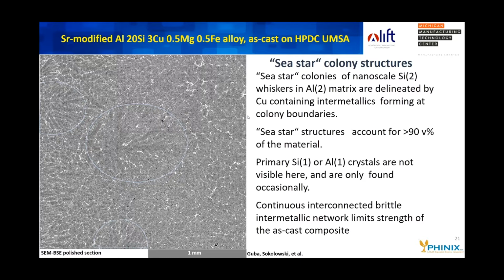The white material in the picture is bright because it contains copper and backscatters the electrons well. So you can see that the copper intermetallics form continuous bridges through the material at the colony boundaries. However, the interior structure of the sea star colonies, the Al2 and Si2, account for more than 90% of the material. And even at this low magnification, one does not see either primary aluminum or primary silicon.